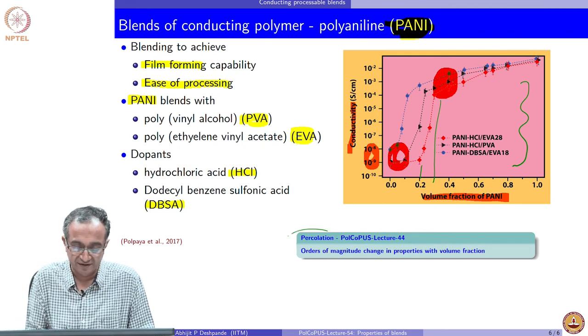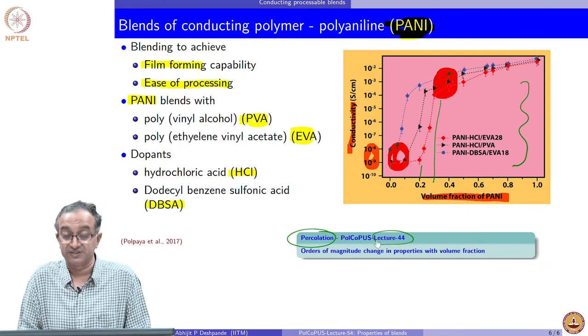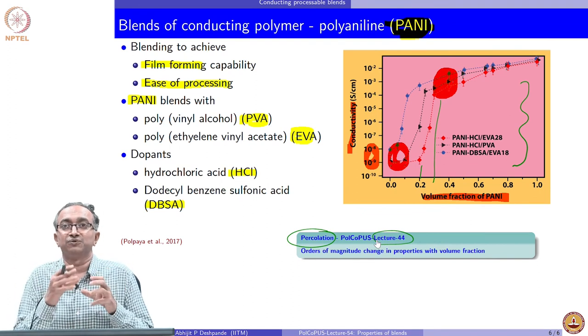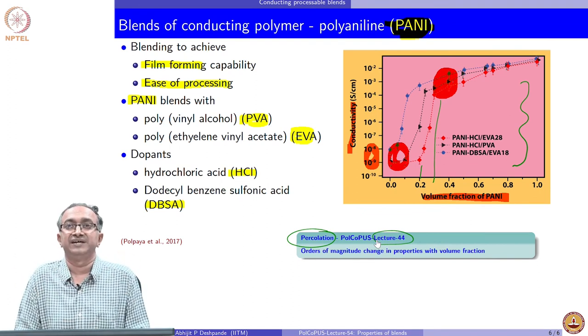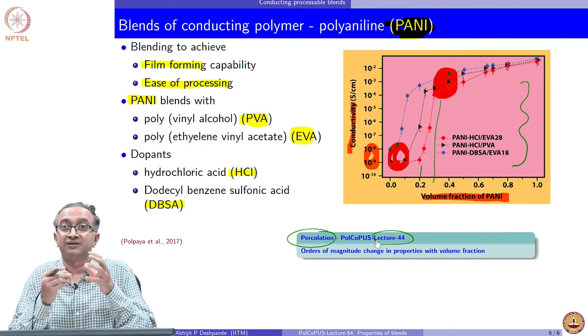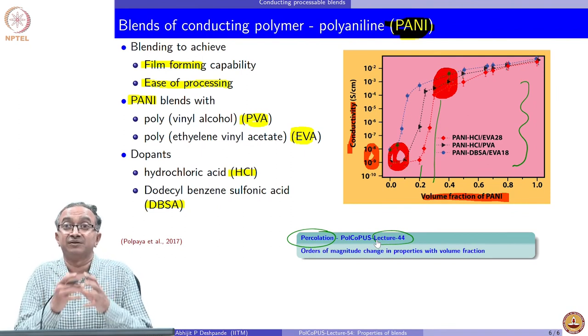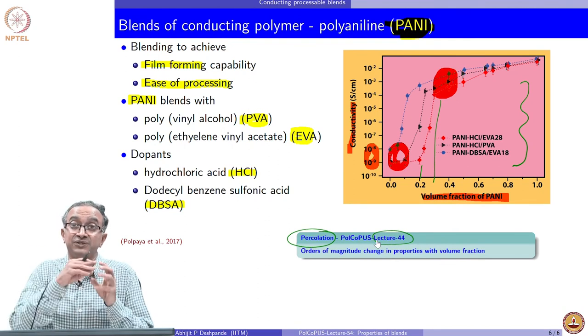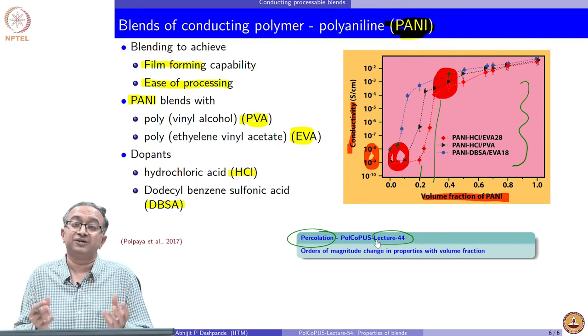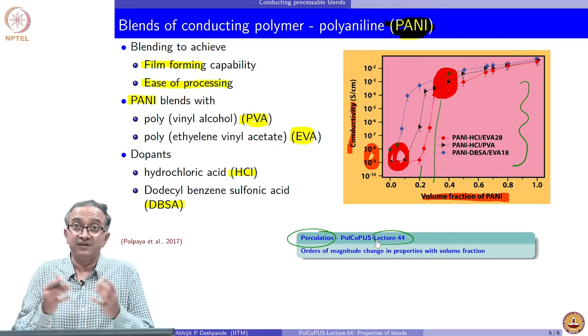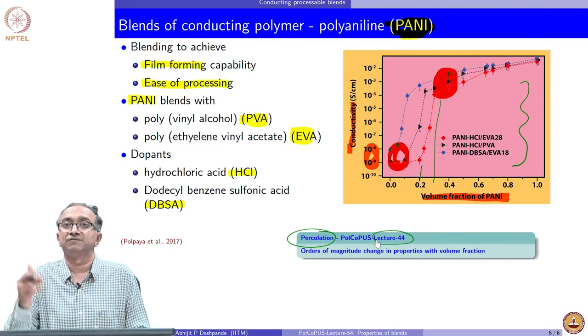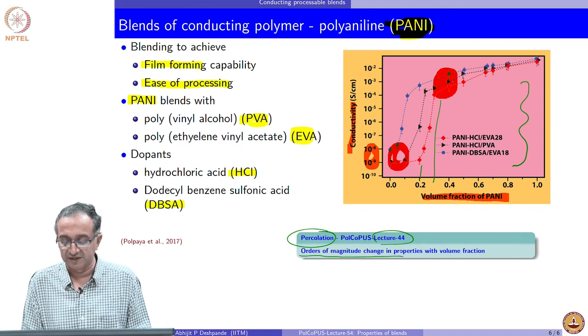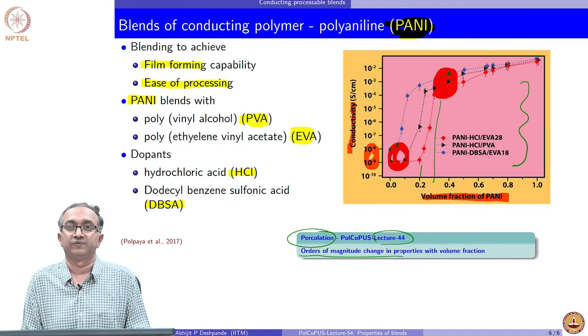Immediately you should recall that what we had discussed in lecture 44, this is the percolation. Polyaniline is distributed throughout PVA and EVA phase. But beyond a certain volume fraction, all these get interconnected and that percolation is reached and therefore, conductivity increases very significantly. Now, since it is polyaniline domains which are all connected to each other, conductivity is very close to bulk conductivity, which is very synonymous with orders of magnitude change in properties with volume fraction.